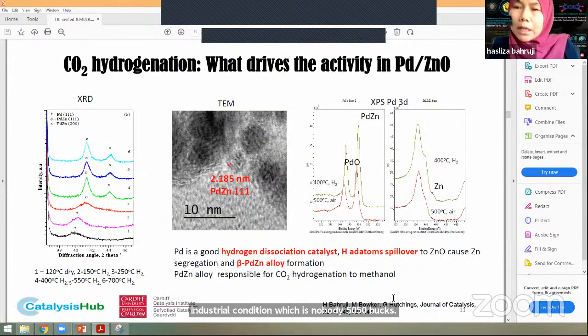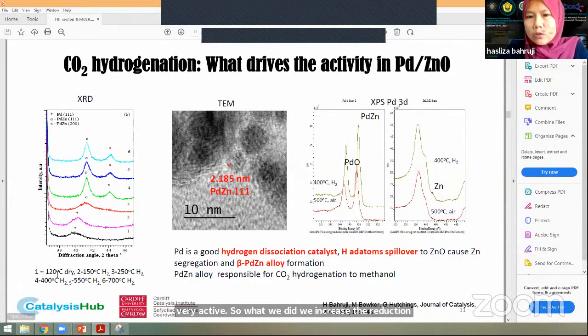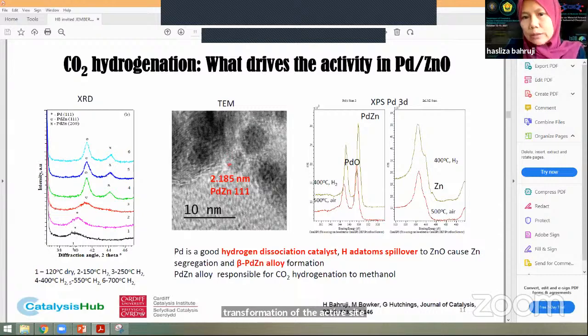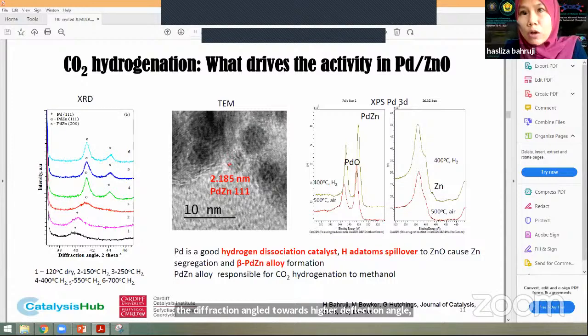So we tried to understand why palladium zinc oxide is very active. What we did was increase the reduction temperature from 120 degrees Celsius up to 700 degrees Celsius. The XRD peaks that we can see here tell us that there is a transformation of the active site of the catalyst from reduction at 120 up to 700 degrees Celsius. At the very beginning, the palladium exists as palladium 0, in the metal zero oxidation state. But when we increase the temperature up to 400 degrees Celsius, we can see the formation of palladium zinc alloy starting to be observed. The shift of the diffraction angle towards a higher angle gives us an indication that this palladium is transformed into palladium zinc alloy.